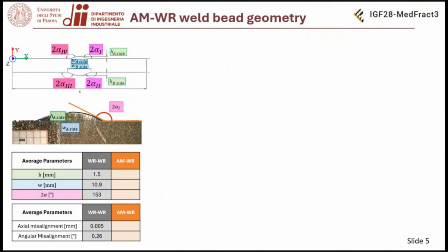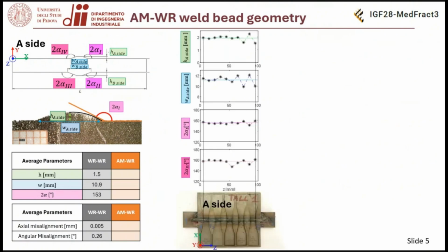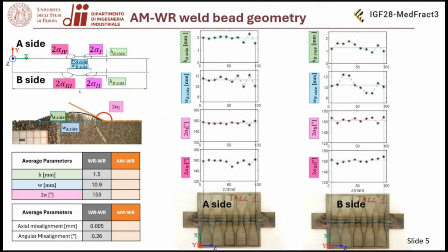We also carried out this characterization for the joints with the AM part, so we acquired all the measurements of the different parameters. And as you can see, the mean values are almost the same as the traditionally manufactured welded joints. In the case of the misalignment, as you can see, they are greater, and this induced us to mill the gripping surface. Then, also in this case, we have some tests with the strain gauge specimens, and we verified that the bending at the failure point was negligible, also in this case, and that the loading ratio that we can measure with the strain gauges was the same as the theoretical one.